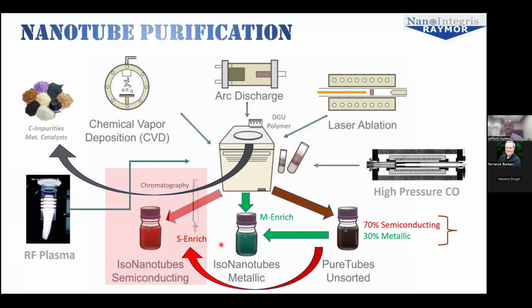Basically, we're two companies in one, NanoIntegris and Raymor. On the NanoIntegris side, we are known for nanotube purification. So we can take nanotubes from various types of production sources, such as chemical vapor deposition, arc discharge, and laser ablation. We remove the carbonaceous impurities and the metal catalyst, and then form a highly pure single wall carbon nanotube solution that can then have its properties enriched to be either completely metallic in nature or semiconducting in nature,